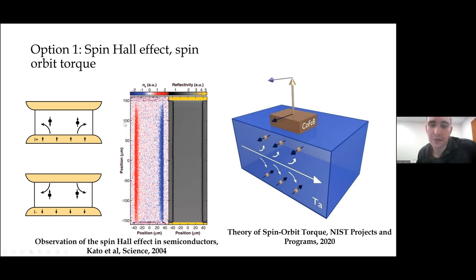What I'm showing at left is a spin Hall effect in gallium arsenide. So when you flow electrons through this semiconductor, there is a finite anomalous velocity associated with the Berry curvature, and electrons of different spin end up on different sides of the device. So this is a spin Hall effect in a semiconducting system. Of course, metallic systems with finite Berry curvature will also have spin Hall effects and will do the same thing. We'll have anomalous velocity and we'll do the same thing.